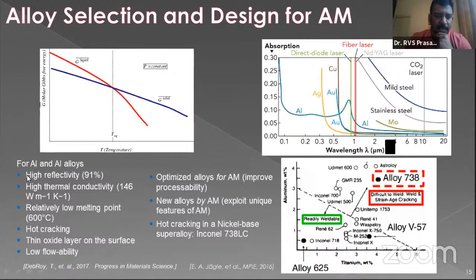Not only that, there are a lot of physical properties like high reflectivity, high thermal conductivity, and the melting point. For example, if you consider aluminum, there is an oxide layer formation on the surface, like Al2O3 will form on the aluminum. All these things should be considered when you are choosing a new alloy. And then when you are developing, even the laser absorption coefficient matters. You have different metals which have different laser absorption coefficients and wavelengths. For example, copper needs a very high laser input. At the same time, for a mild steel or a stainless steel, you don't need a very high laser energy. Copper and aluminum have very high thermal conductivity, so they will quickly dissipate your heat, so that you need more and more laser heat input. But other materials will have a low thermal conductivity, and there it will behave differently.